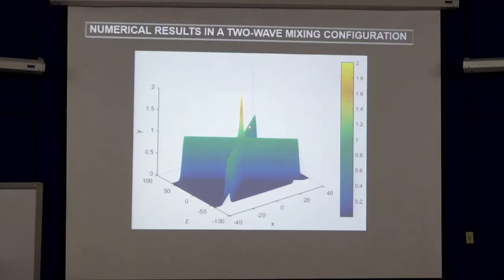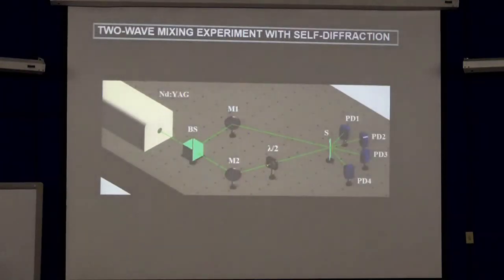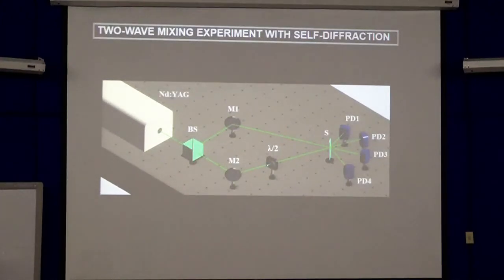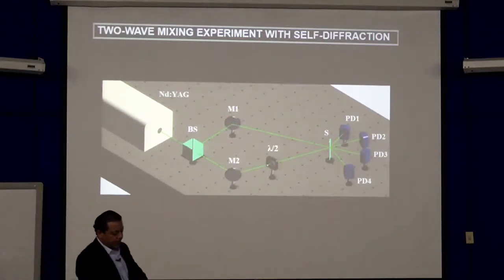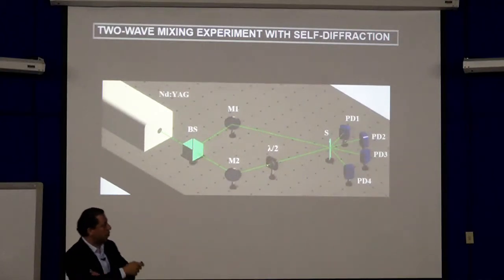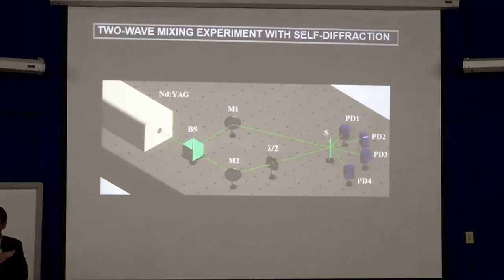There is a transmitted beam, and alongside the transmitted beam, we have a different beam that corresponds to a self-diffraction. So in the lab, we have a laser system that is split in two different beams, and we use a half wave plate in order to control the polarization of the beam. A wave plate originates the rotation of the polarization.